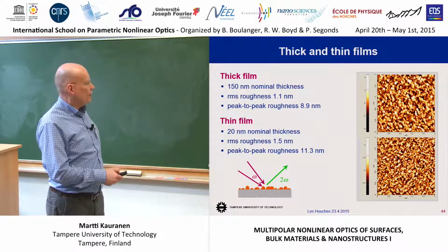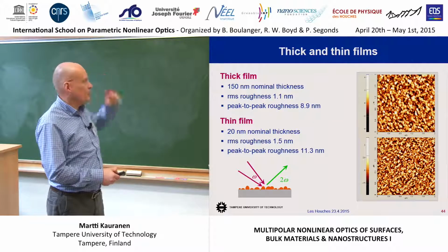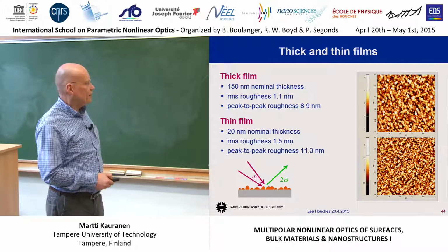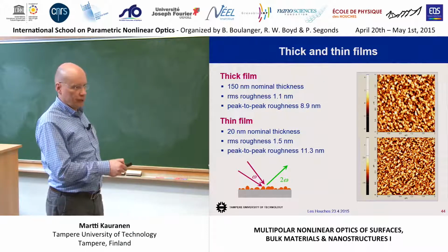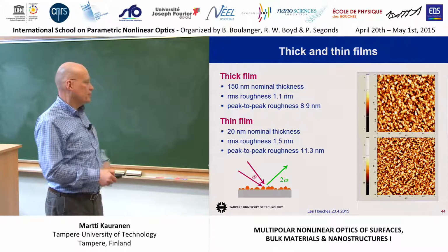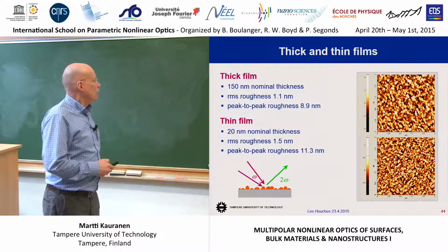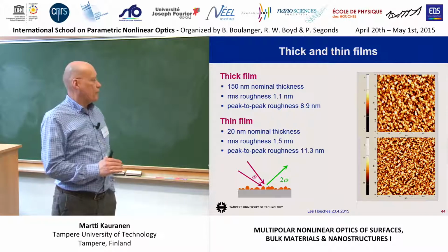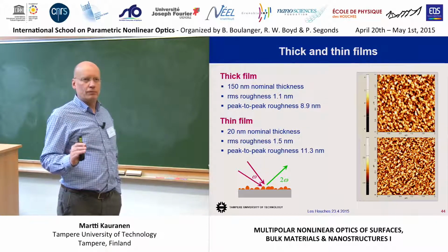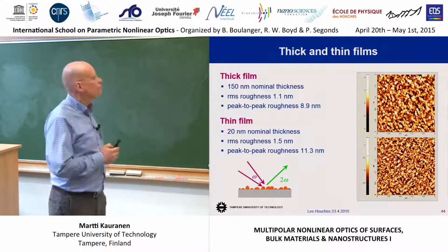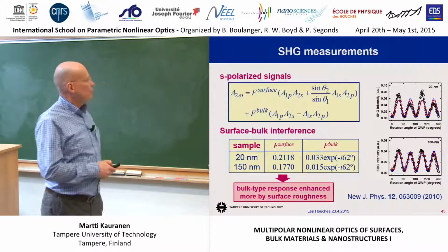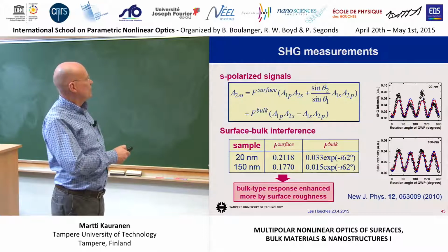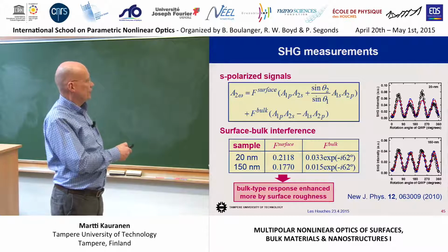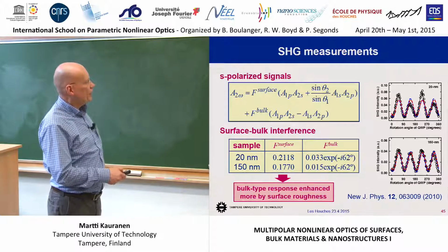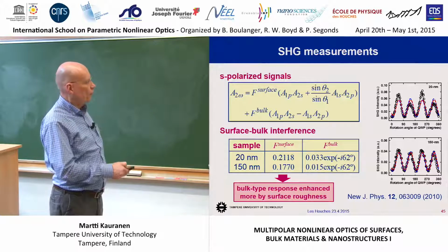And then if you look at the AFM images of these two samples, you can see that the characteristic feature size here is smaller than here. And so in relative terms, this is much more random and rough and so on. So we thought, okay, now we have two samples with different surface structure. So let's see how that influences the response. And then we just use this simple model, the surface part and bulk part for the S-polarized signals. This is our 20 nanometer sample, the new sample. This is the old one.